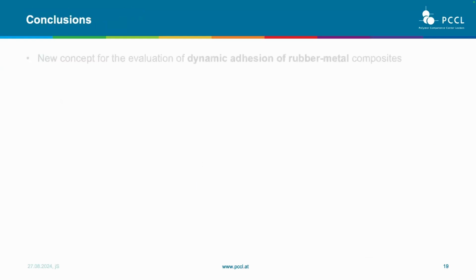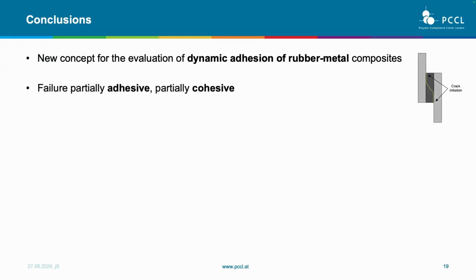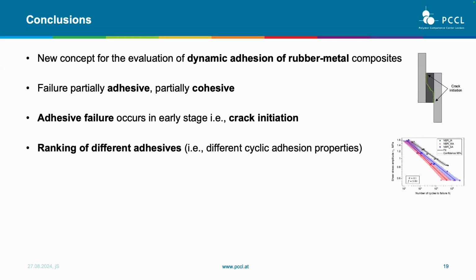So to conclude, we wanted to investigate the dynamic adhesion of these rubber-metal composites. To do this, we used a lab shear specimen, and we obtained something that is partially adhesive and partially cohesive. Nevertheless, the crack initiation is of course at the interface, and so some information on adhesion can be obtained. Moreover, this method is able to provide a ranking, and so can give some information especially about the cyclic adhesion properties. This is really a more technological aspect, so it's good for company partners that can take their different materials, test them, get a ranking and decide what is best for their material.